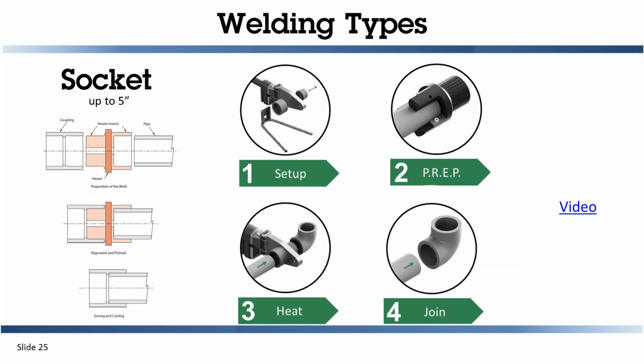Socket fusion has a heated tool, which is the red component in the middle of that picture. On one side, you put the coupling or fitting. On the other side, you insert the pipe. After just a few seconds, they come to temperature, and once they're at temperature, you remove them from the tool and stick it together. One of the critical aspects of this type of weld is people are transitioning typically from the knowledge of PVC to this sort of installation. It's important that the joiner does not twist the coupling and pipe. It's a common practice in PVC solvent cement, but it does not apply here. It's just a straight on, straight out fitting.